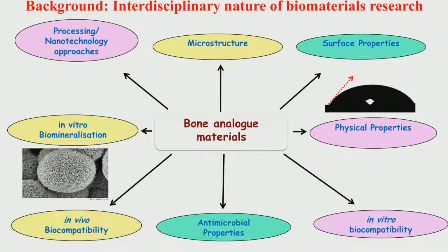Now, in vivo biocompatibility is to be assessed using an appropriate animal model. Since bone has hydroxyapatite as one of its inorganic phases, if some material does not have hydroxyapatite as one of its microstructural constituents, one of the very important things to see is whether this material can induce calcium phosphate nodule formation when immersed in simulated body fluid over a certain time period, which can be a few days to a few weeks.